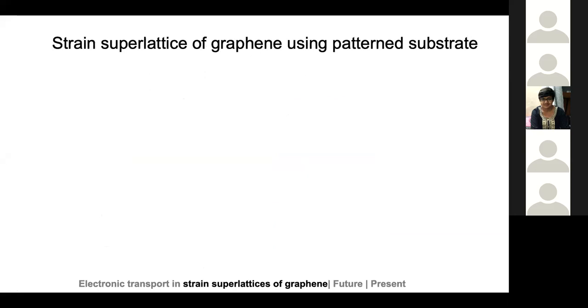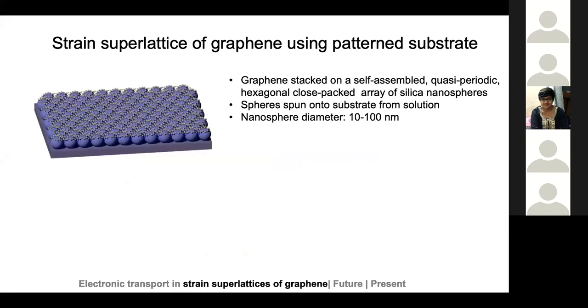What our group has been trying to study for the past few years are strain superlattices using patterned substrate. So the idea is to spin coat a solution of nanoparticles. We use nanospheres initially, silicon dioxide nanospheres onto a silicon dioxide silicon chip. And it was found that these nanospheres form these hexagonal closed packed structures on their own. There are large areas, polycrystalline areas, and you can find very regular closed pack structures of these nanoparticles. And then graphene was wet transferred onto the system.